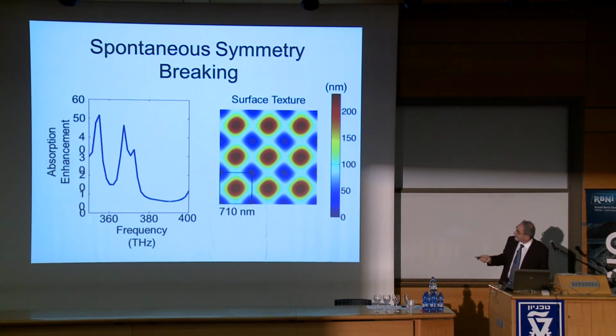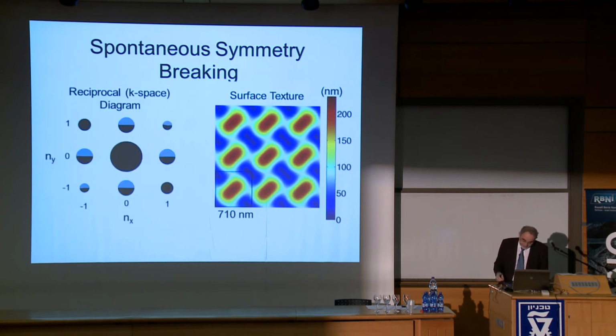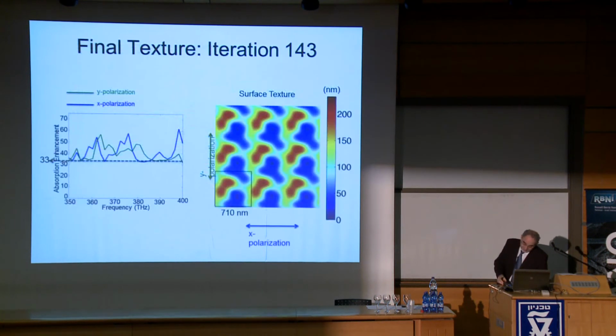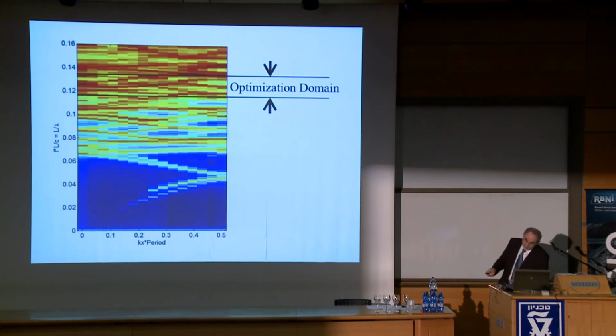The result of this iterative, mathematical procedure is to come up with some shapes that are breaking the plane parallel symmetry. If we restrict it to some type of symmetry, starting with random perturbations, we end up with these oval-shaped structures. And in fact, if we allow it to evolve further, we find out that the optimum domain for trapping light in the thin film is very high in the photonic band structure. So this turns out to be the optimal region.